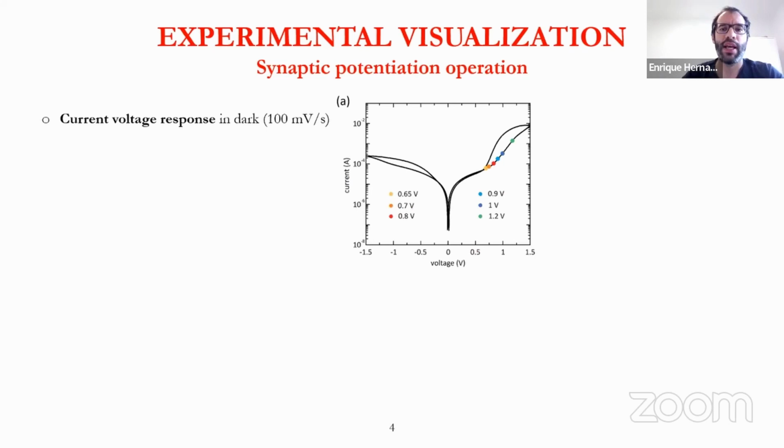At the first point, we develop a current-voltage measurement, and we obtain this J-V curve, in which appears the inverted hysteresis explained previously. The inverted hysteresis consists of the current measured in the forward direction being lower than that recorded in the reverse direction. It appears bipolar, okay? It appears for positive voltage and for negative values of voltage, okay?